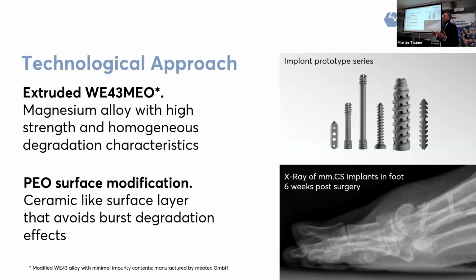And all these devices, which we offer at Medical Magnesium, rely on a combined technological approach. They are based on the alloy WE43 MEO, which is an alloy Max just recently introduced to you, that offers for our purpose high strength and homogeneous degradation performance. And we combine this with a PEO surface modification, like a ceramic top layer, which delays the initial degradation reaction. So we decrease the hydrogen release into the adjacent tissue by this surface modification. And this way, we avoid burst degradation effects we could potentially see in the tissue.